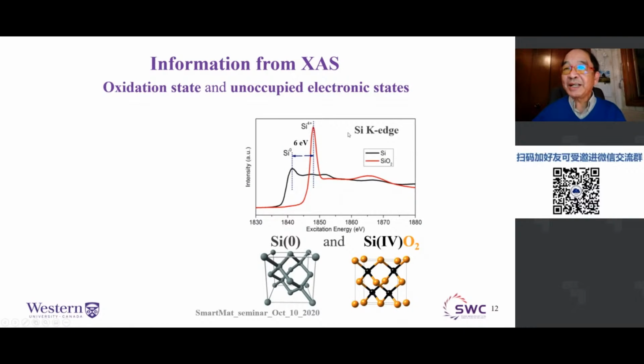And here are the two absorption spectra of silicon, one in the chemical environment of pure silicon, and the other in silicon oxide. Obviously, there's a huge difference in oxidation states. So let's look at the silicon. When the threshold energy is reached, the 1s electron gets excited and propagates away, and it sees the neighboring atoms and brings all that information back, and the result is the absorption spectrum of silicon. Similarly, when you excite the 1s electron in silicon oxide, the photoelectron goes out and sees the neighboring atom of silicon in the first cell, and then oxygen in the first cell, and then silicon in the second cell. It brings back all that information, and it produces this absorption spectrum. So in principle, the absorption spectrum contains all the information about the neighboring atoms.